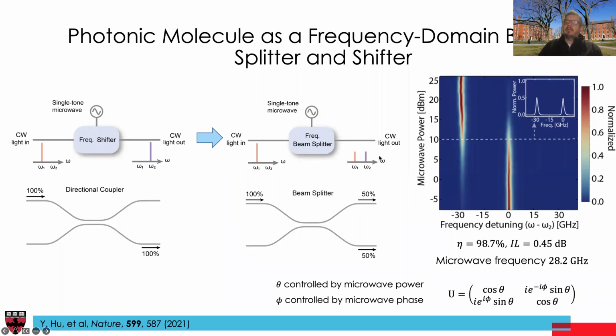Going back to the beam splitter, basically we have a frequency shifter. In this case, the device with splitting was 30 gig, not 12. And what this shows is how much light we have in one optical resonance versus another optical resonance as we are changing microwave power. So originally I put all the light in one optical mode, and I'm slowly dialing up RF power. And you see at some point I have a 50-50 split between the two resonances. And this is when I perform frequency beam splitter functionality. And then I keep dialing up the power, and now all of the light is moved to the second resonance, and this is the frequency shifter functionality.